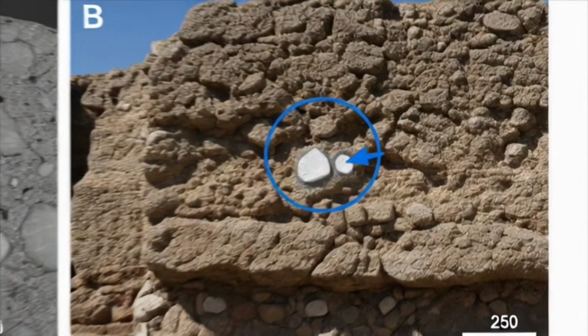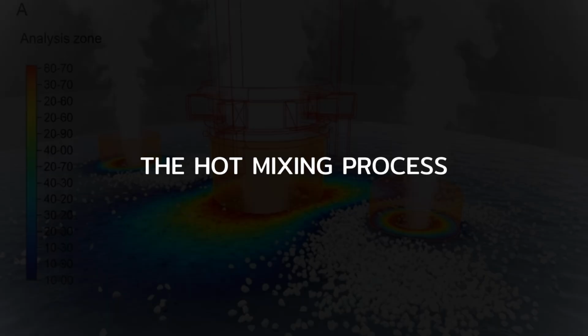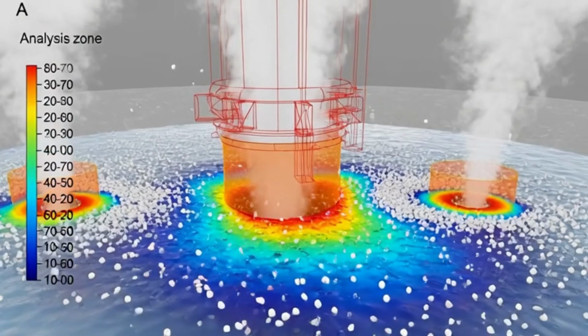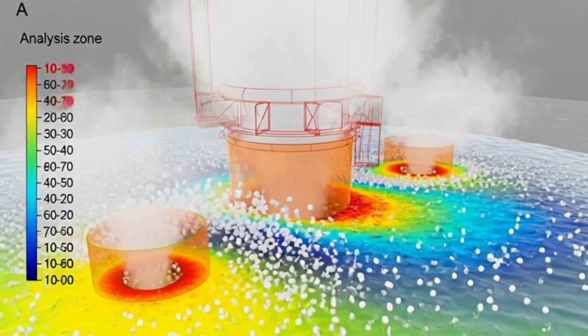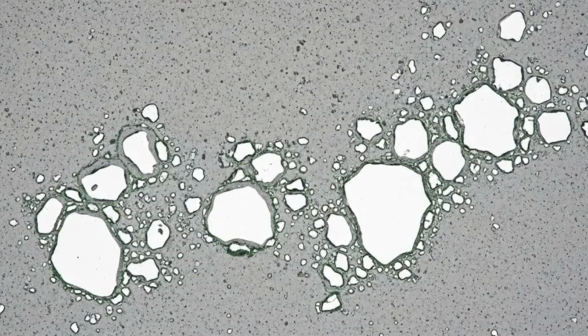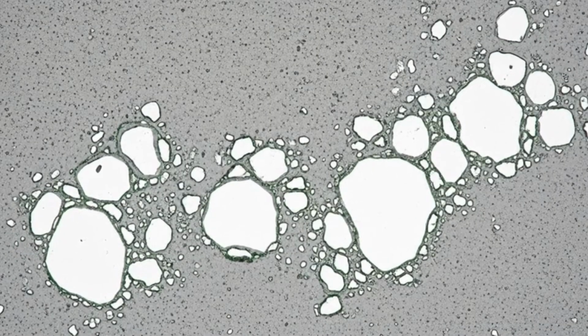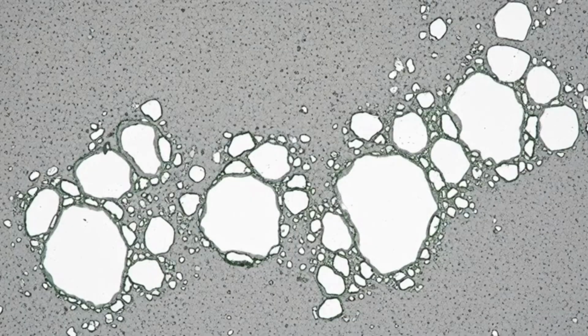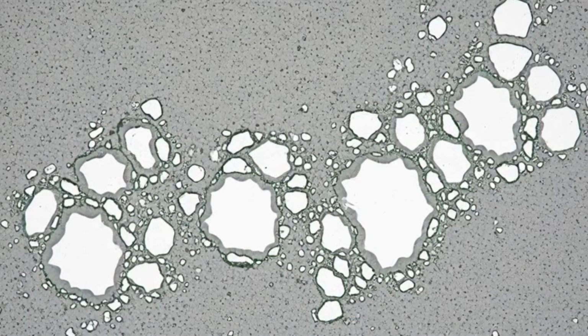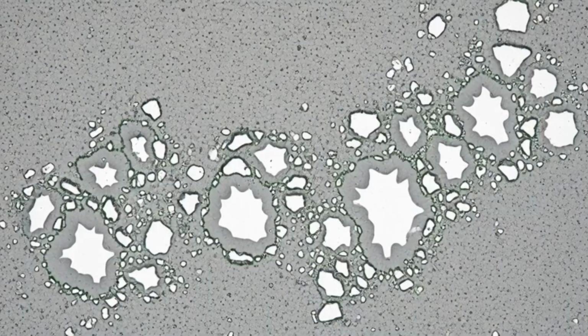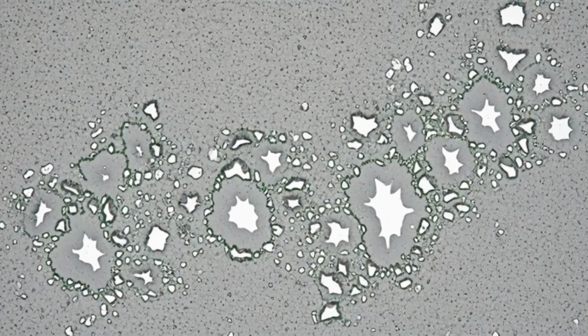But the evidence is clear. The lime clasts are quicklime derived. They exist throughout Roman structures. The hot mixing process: add quicklime directly to the mix, add water, and a violent reaction occurs. Temperature spikes to 200 to 300 degrees Celsius locally around quicklime particles. Steam generation and turbulent mixing create two effects: better distribution of lime throughout the mix, and residual quicklime pockets. These pockets don't fully react. They remain as lime clasts, high calcium islands in the concrete matrix.